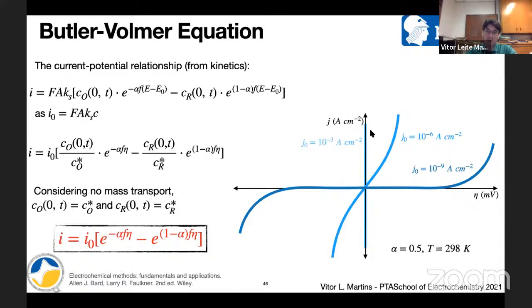And here's how the current that we measure is changing with potential when we change the exchange current. So for a very small exchange current, we have a curve like that. So we need a larger overpotential for the current to occur. Remember, this means that we have a higher resistance. Remember that from the polarizable electrode. So a higher resistance to the electron transfer means that this reaction has a low exchange current. That's why you get a profile like that.